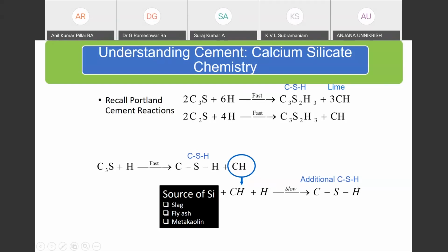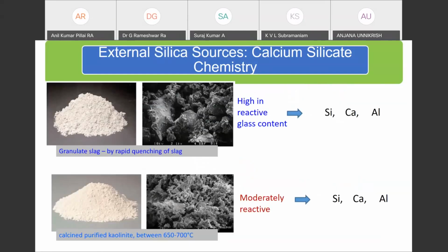And we discovered these have been in use. So that has allowed us to reduce the clinker factor of cements. And now the cement companies, working with the researchers, working with the standardization agencies, have standardized the addition of these supplementary cementitious materials. So slag, fly ash, metakaolin, these are all supplementary cementitious materials, which are used as a replacement of cement in Portland cement. So now this has become commercial, where we're able to reduce the clinker factor with the use of these waste materials. So just to give you a little background of these waste materials, we use slag in a granulated form. It's basically the junk or the gunk that floats on top of molten steel that is quenched very quickly, and it produces a highly reactive glass, which is what we know as slag. And the slag is very rich in silica and calcium, which are the main ingredients of cement. And so we are able to use it as a cement replacement.